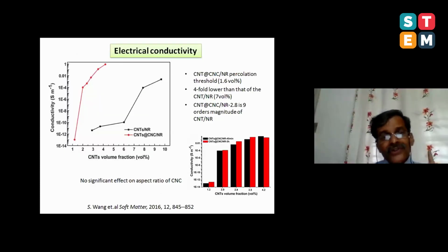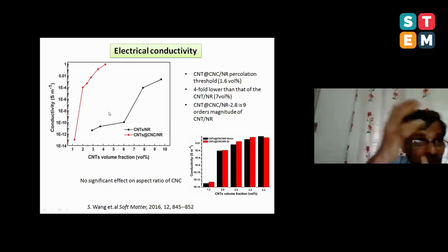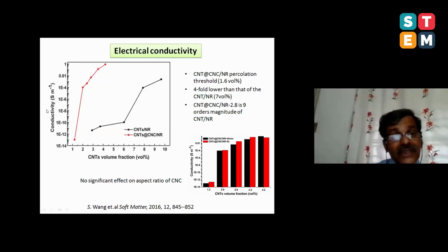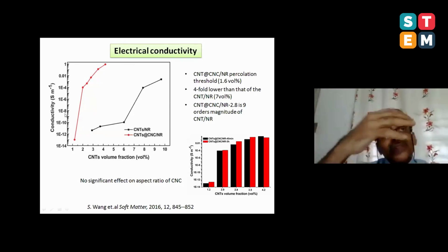And I can show you another interesting slide. This is the percolation process, conductivity as a function of CNT volume fraction in natural rubber. Look, you get percolation here if you use CNT alone after adding 7 volume fraction of CNT in natural rubber. But if you use a combination of CNT and nanocellulose together, you get percolation by adding just 1%. See, the percolation is shifted to lower concentration of CNT by combining nanocellulose and CNT together.